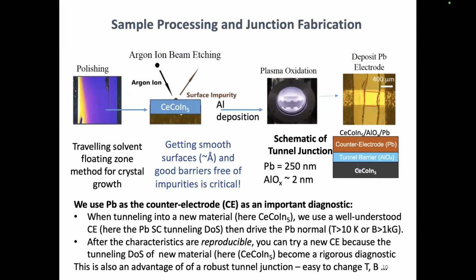To remind you, some of you have been to this talk before, we do a lot of polishing and etching. In this case, we plasma oxidize the surface to make the barrier. So if you focus on right here, we have the highly polished CeCoIn5, in this case, an aluminum oxide plasma oxidized barrier and a counter electrode of lead.